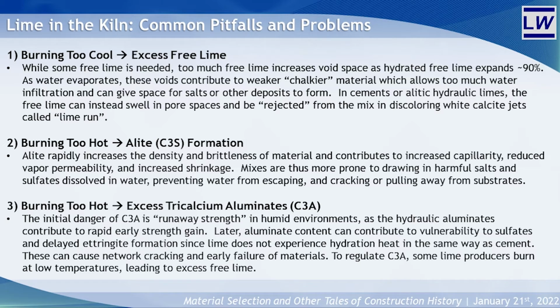While this may not be a problem for certain hardy masonry, it can be especially problematic in soft masonry, where the low density and compressive strength of an NHL2 is often specified. Less commonly, but still a threat, high C3A limes can swell in the presence of sulfates due to delayed ettringite formation, leading to cracking and weakening of the material. To prevent the formation of excess C3A, producers may undercook their lime, which can result in excess free lime, leading us back to the problem discussed in point number 1.